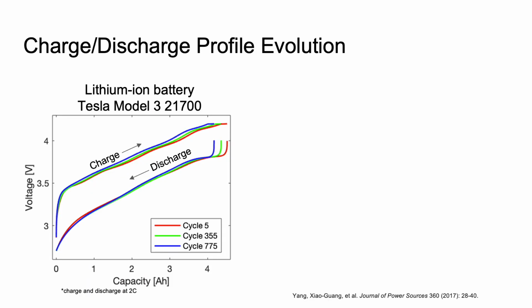One of the fundamental figures for batteries is their voltage response as they are charged and discharged. Here we are viewing the charge and discharge profiles of the battery inside a Tesla Model 3. As you can see, as the battery is charged, its voltage increases. As the lithium-ion battery undergoes extended use, shown by the curve sequence red to green to blue, various degradation mechanisms occur which cause shifts in these charge-discharge profiles.